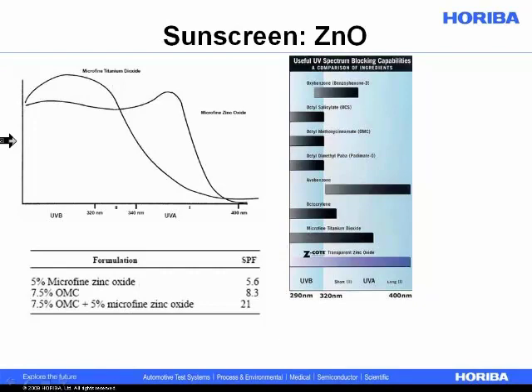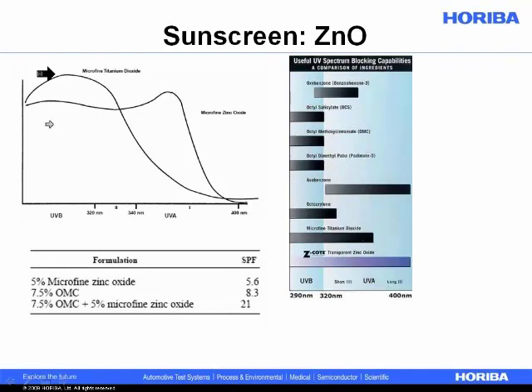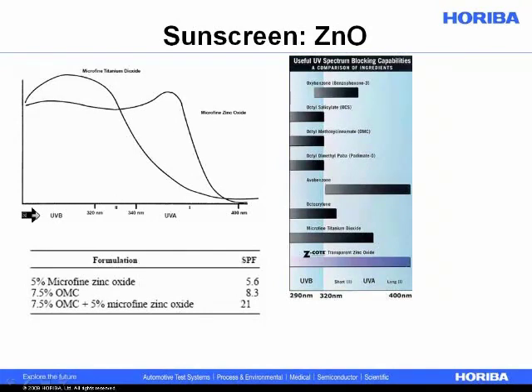In the upper left is the absorption spectrum for this particular zinc oxide — wavelength on the x-axis, absorption on the y-axis — showing zinc oxide and titanium dioxide. As I choose which powder to add to my sunscreen formulation, what makes sense is the broadest absorption band available. This particular zinc oxide formulation actually absorbs all the way up to 400 nanometers, covering not only the UVB range but also the UVA range. So if I were creating a sunscreen, I might choose zinc oxide because it has a very broad spectrum of absorption.